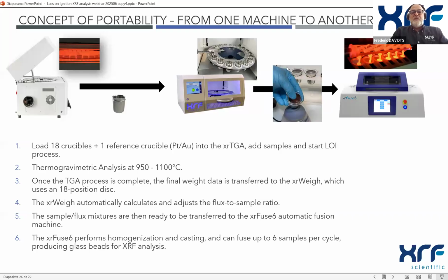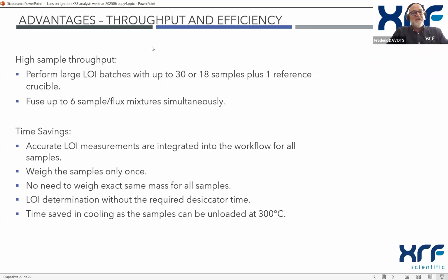And of course, between the xrWeigh and the fusion, we will probably mix the flux and the sample directly in the crucibles using a vortex mixer, for example. That's an important step, of course. It works with samples that are not caking, but in the case of ores and iron ore, where we made the most tests, there is no problem at all.